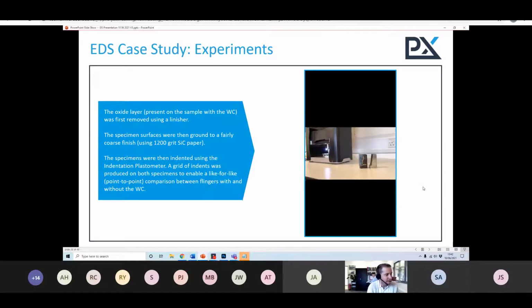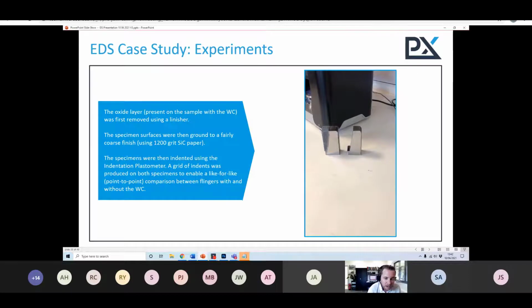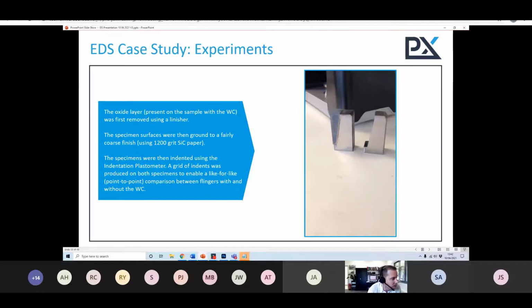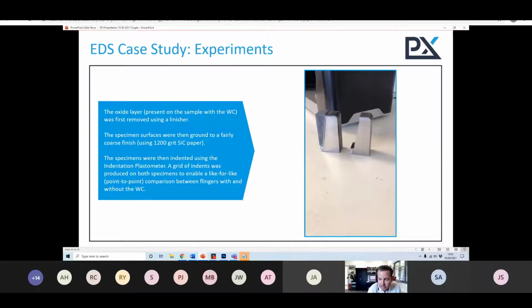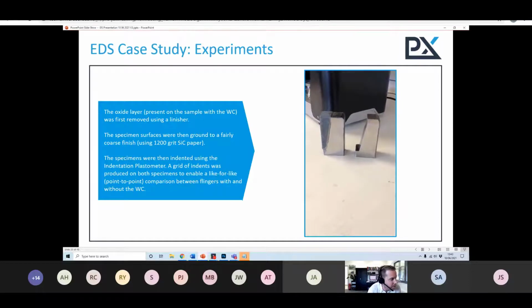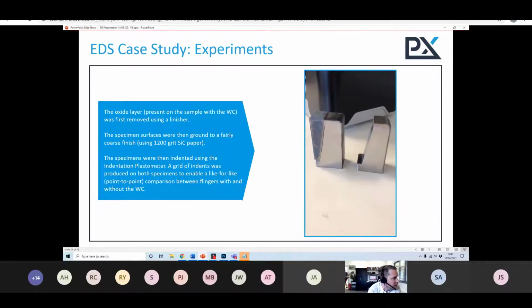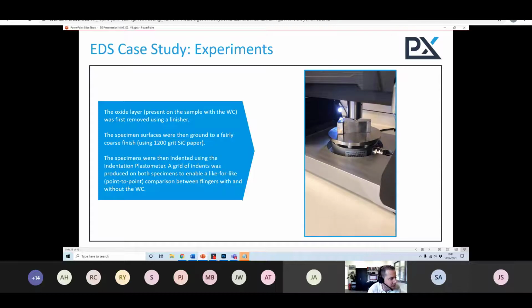So what we did then, as you can see in that video, is we took these two components. What we had to do with the one that had been brazed, though, was essentially remove that surface oxide layer, which is quite a sensible thing to do, because in that particular case it was very thick. So we've cleaned it up, and it's had a polish and a grind. And then those materials have been inserted into indentation plastometry. You can see an indentation process taking place there.